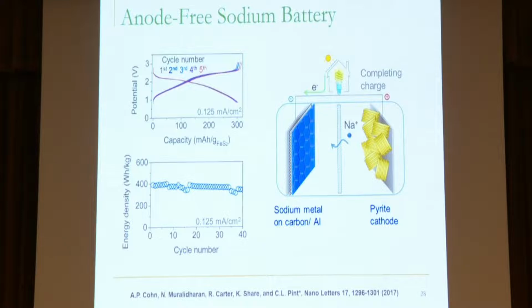Now, this is pretty exciting. When we did this, we are actually able to measure, so these are charge-discharge curves from the battery, but more importantly, when we integrate the area underneath that curve, which gives us the total energy stored, and we divide that out by the total mass of all the materials, we get the total energy density of our battery.